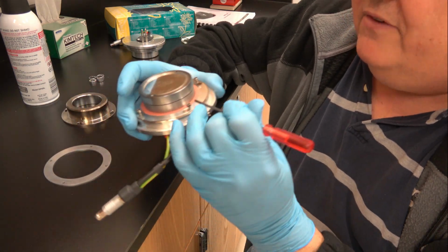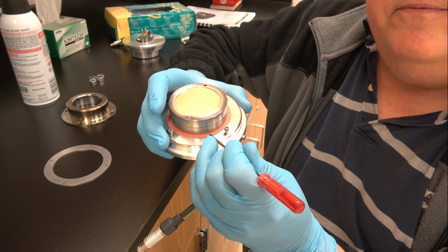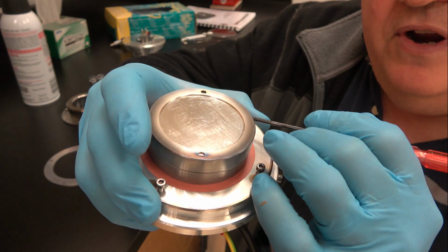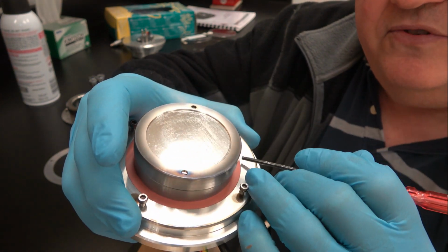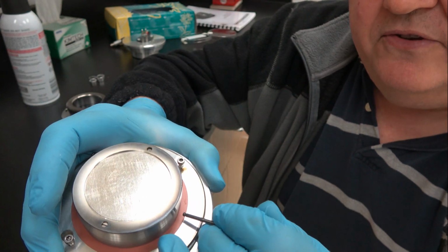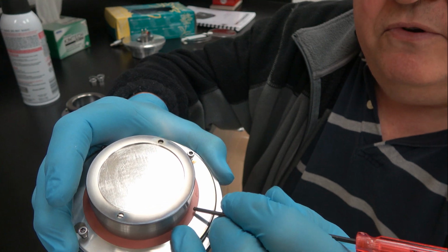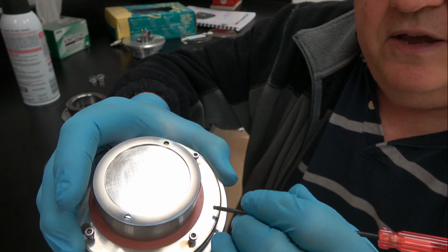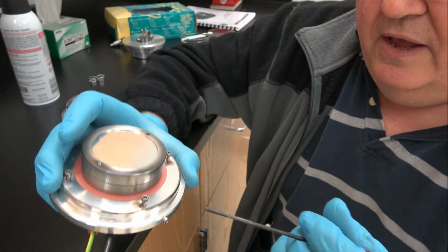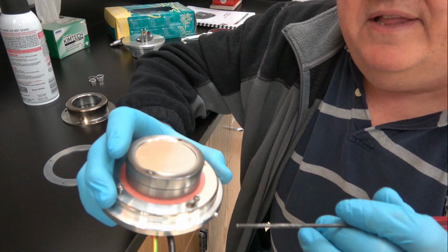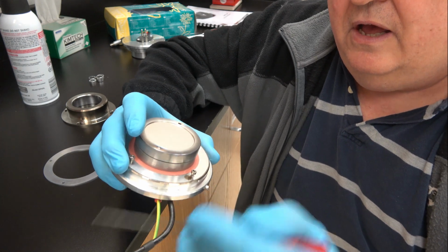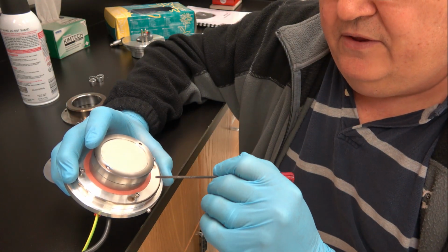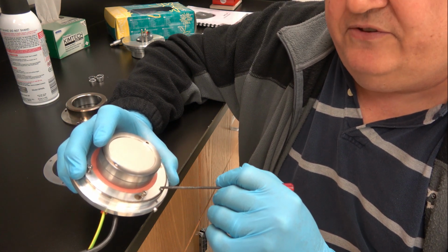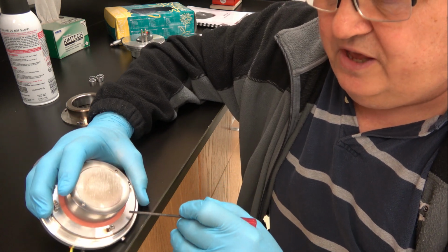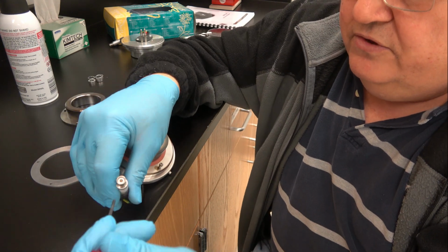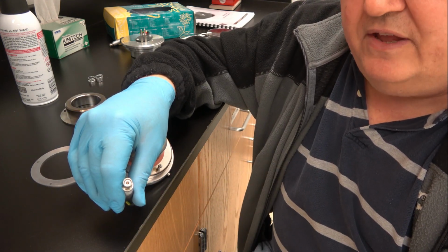So the other possible short is this is an insulator, this material right here. It goes underneath the entire sputter head assembly that's in the vacuum system. Sometimes this can arc because you're using high voltage and it burns through this insulator material and now is shorting directly to the metal of the insert. You may or may not be able to diagnose it via an ohmmeter. If you touch your ohmmeter to here and to here, it should show very high resistance in the megohm range. If you touch the one lead of the ohmmeter from here to the center pin, you should have high resistance.